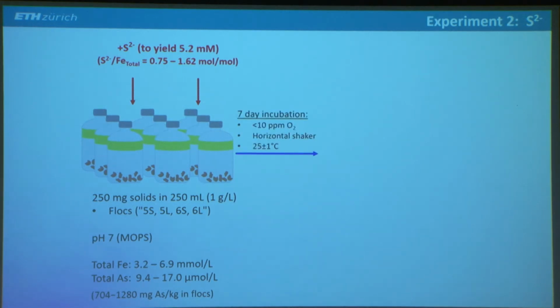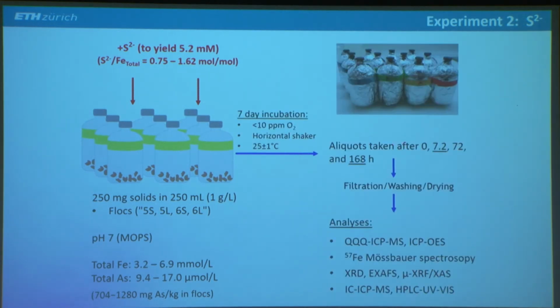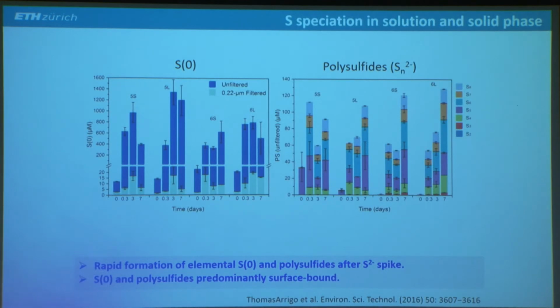We incubated the samples for 7 days, again took aliquots after different time intervals, prepared them, and used various techniques to analyze the solution and solid phases. So I want to first show you what happened with the sulfur. So this shows on the left side elemental sulfur, and this is for these 4 different flock samples, always showing 0, 0.3, 3, and 7-day incubation.